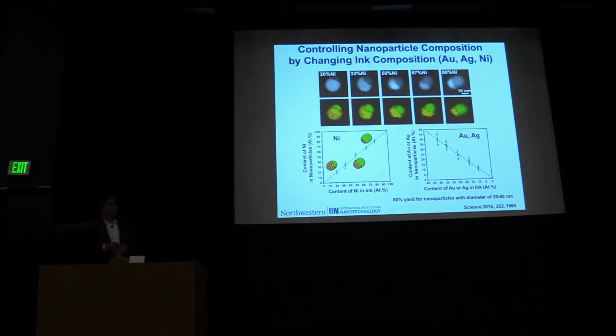Whatever you put in the polymer ends up in the reactor. You can see this, and that's critical if we want to do what I'm talking about with respect to megalibraries. So here's an alloy particle, a heterostructure actually, that has an alloy of silver and gold and nickel on the outside. So this part is silver and gold. You're looking at EDAX, the color coding here for the elemental map. The nickel is the green region, and you can see we dialed in intentionally 20% nickel, 33%, 50%, 67%, 80%.